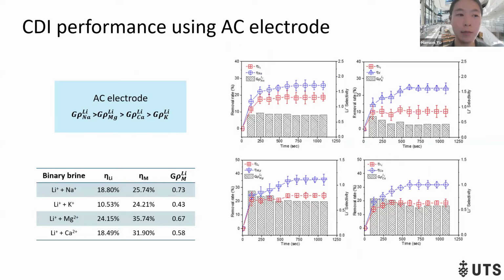Now let's see the CDI performance of using these electrodes. Using the AC electrode, the adsorption selectivity of lithium to sodium is 0.73. For lithium to potassium it is 0.43, lithium to magnesium is 0.67, and lithium to calcium is 0.58.